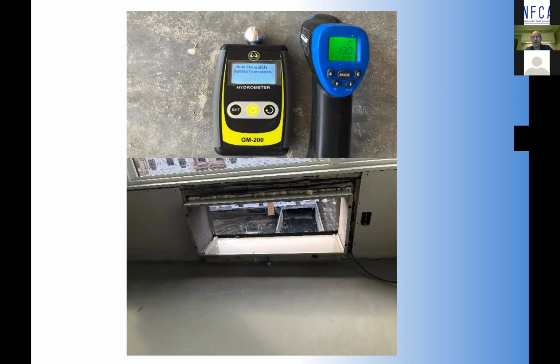One thing that I carry around, as do a lot of contractors, is an electronic digital laser temperature tester, where you can get a pretty quick and easy reading of your slab temperatures. We can do all kinds of preparation work, like patching and self-leveling, at 10, 12, or 13 Celsius. That's not a big deal. It's when we get into the actual flooring installation that we have to have proper temperatures of 18 Celsius or above.